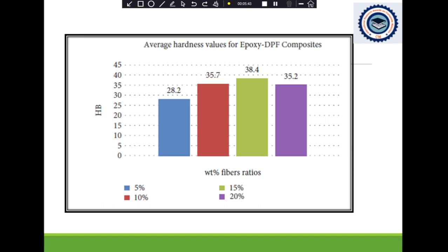The maximum was for the 15 weight ratio of fibers, and this maximum result is due to good bonding between the matrix and fiber. As a result, when we increase the ratio of the fiber, the hardness decreases due to a lot of porosities during the pouring of the mixture into our silicon mold, and also due to increased impurity inside the structure of the composites.